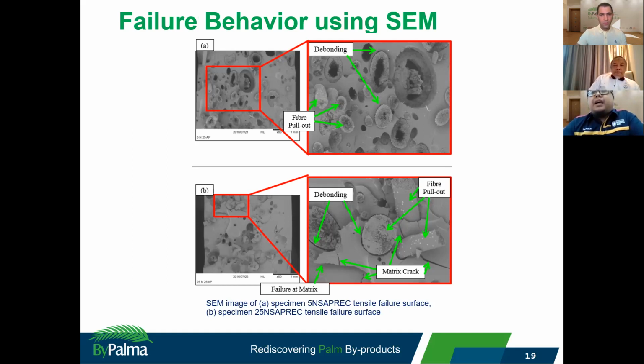As we can see in the SEM image, the matrix cracking occurred more severely in the 25 nanosilica specimen compared to the 5 at the top. Improper wetting was also caused by nanosilica mixed with epoxy resin, which increased the viscosity of the mixture compared to pure epoxy resin.